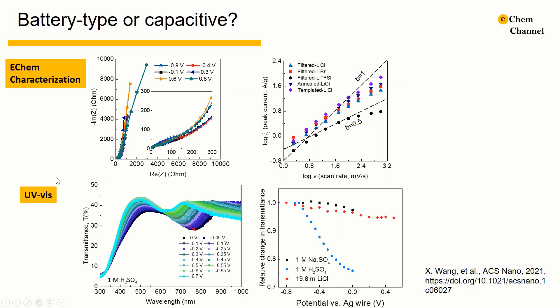Next, we use UV-Vis spectroscopy to observe the change of oxidation state of titanium in Ti3C2. The position and intensity of the plasmon resonance peaks of titanium carbide are known to shift during changes in the oxidation state of titanium, caused by the transfer of charge from lithium to the oxygen terminations of MXene. At the peak potentials in the CV recorded in sulfuric acid electrolyte, the rate of transmittance change increases, suggesting that the rate of charge transfer increases at the redox peak potential. Conversely, in 19.8 mol/kg lithium chloride electrolyte, the UV-Vis transmittance decreases at a slow and almost constant rate with increasing potential. This indicates that the faradaic process accompanying the peaks in the CV in the water-in-salt electrolyte is much weaker than that of the surface redox in sulfuric acid electrolyte.